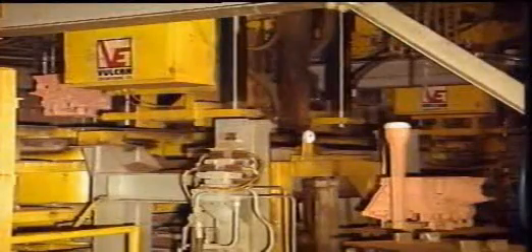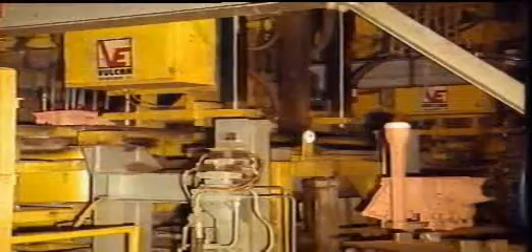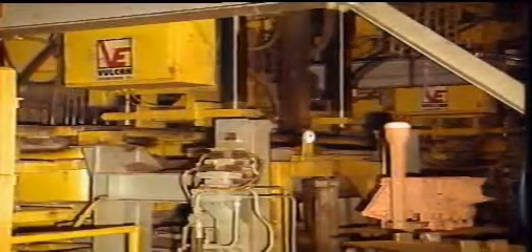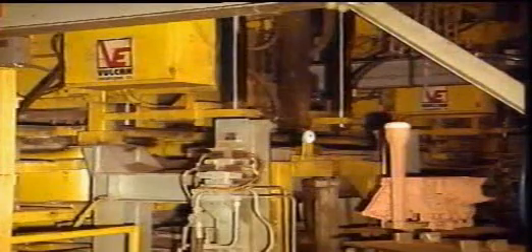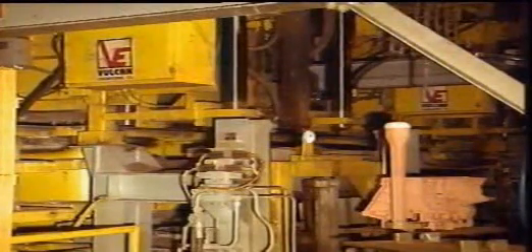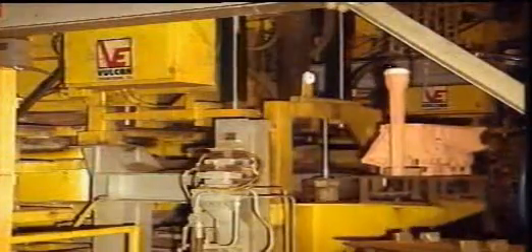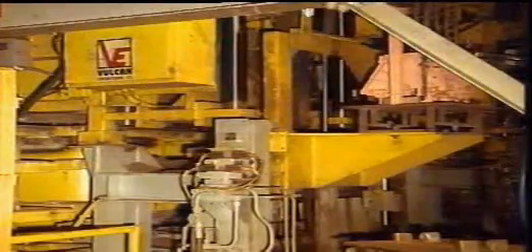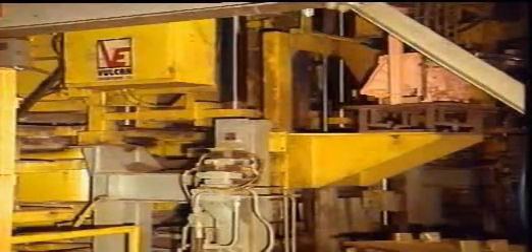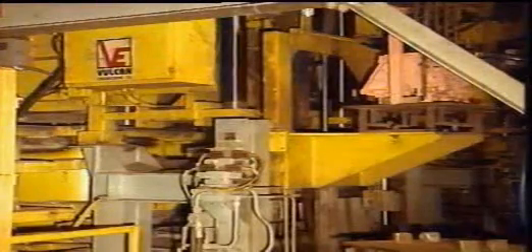The coated dried cluster is then inserted into a special steel flask where dry, unbonded sand is rained around it. The sand must be made to flow into and around the foam without distorting it. The sand filling, together with varying amounts of vibration, must be used simultaneously to fluidize and to compact the sand into all of the internal passages. Control and repeatability are critical in this phase.